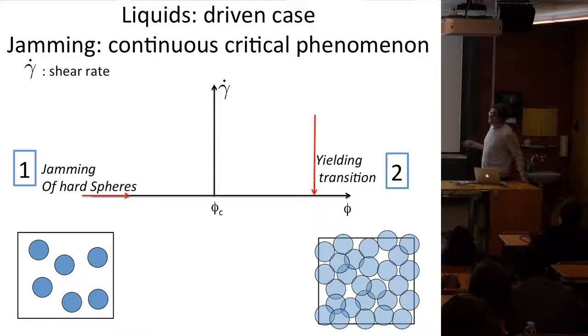So as gamma dot increases, it means that the shear stress also increases. So there are two different phenomena that can happen. One is if you're very close to this line here. So in this region, the strain rate is small. It means that the stress is small. It means that the particles are essentially not deformed. So you can think about really hard particles. So that models, say, a dense granular flow. So that's this region.